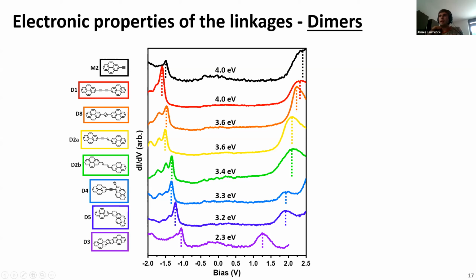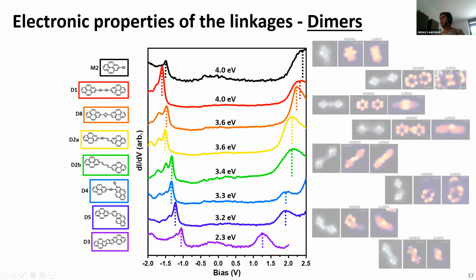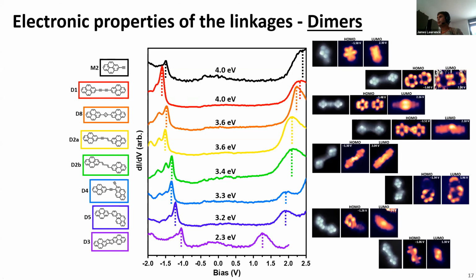But there are some other patterns we see as well. For example, we can see going from this Glaser-coupled dimer, where there's clearly not very much conjugation between these two, because it has a very similar energy gap to the monomer, you can see forming these double bonds increases the amount of conjugation and reduces the HOMO-LUMO gap, as well as directly forming bonds to the pyrene itself in a different position. And of course, these fused rings as well. We've got lots of nice dI/dV images as well of all these different states, and I'll talk about a couple of these in a couple of slides' time.